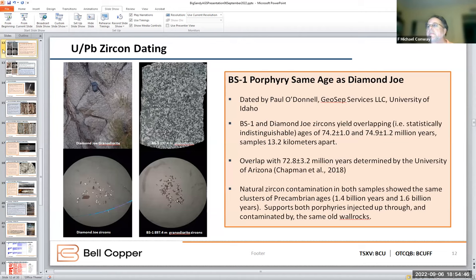All right. So there's a piece of core on the right, a semicircular segment of a circle piece of core from about 900 meters down at granodiorite. And then an outcrop to the left of that from the Diamond Joe stock. So our core hole and the Diamond Joe stock are 13 kilometers apart. Over the Christmas of 2020, I picked the zircons out of both of them, sent them up to the University of Idaho for dating, and the ages came back 74.2 and 74.9, both of them plus or minus about a million years. So they're indistinguishable in age. So at least permissibly, I had found the top of something the same age as Diamond Joe, which is really what I set out to do, and hopefully with some copper in it.